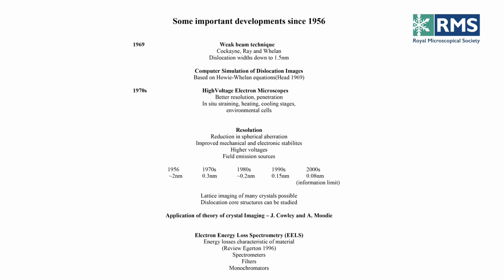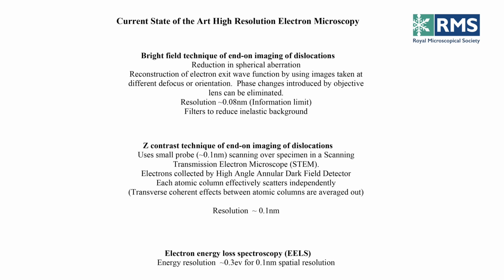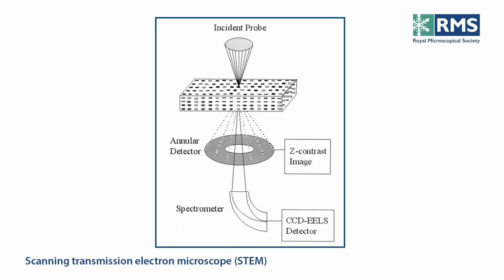and similar chemical reactions. If I could just say something about the current state of the art. I'm probably interested in what you feel some of the more important developments are up to the current date. Well, I think the most important development was the development of the aberration corrector. The other important thing which happened was the development of the so-called Z-contrast technique. Now we'll go over to the STEM system, where you have an incident probe of diameter maybe an angstrom or so, which you can get down to by using an aberration corrector.